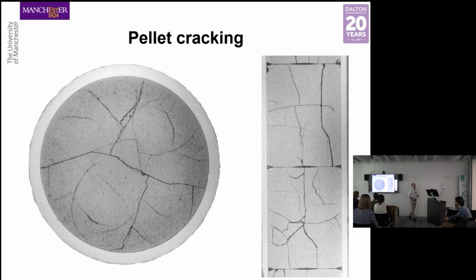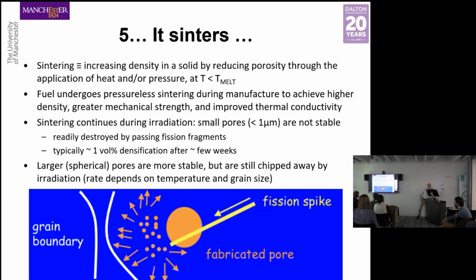So indeed, the pellet does crack. When does it crack? Well, pretty much straight away. As soon as we go up in power, as soon as the reactor has reached full operating power, our nice, beautiful, fully dense pellets have all cracked, all of them. And that itself leads to other problems as well.